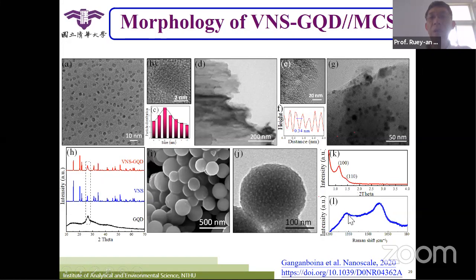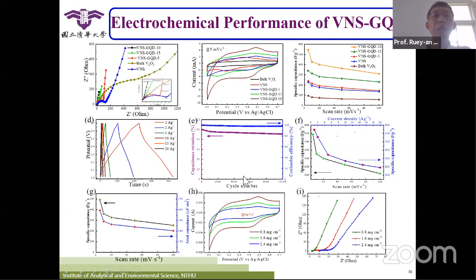And from the Raman spectroscopy, we also can see the D and G band here. So we use these two together and their electrode properties will be good. Here is the case we have the VNS-GQD. The value can be around 550 farads per gram. And if we have the mesoporous carbon, their value will also be around 550.